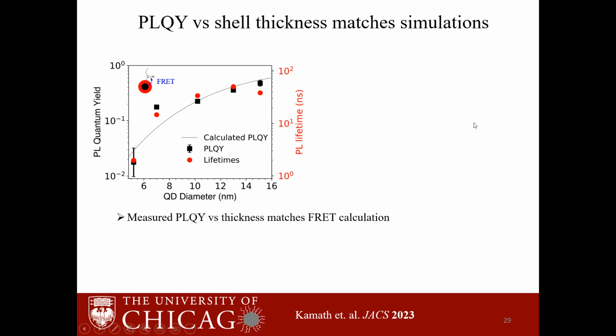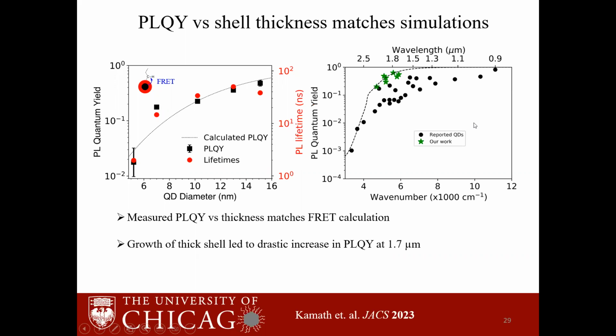And this is a further confirmation that the ligand FRET is not just dominant in the midwave, but also in the shortwave infrared. When we plot our quantum yields with the reported dots, we see that the quantum yields are much brighter than the previous materials. And while the previous brightest materials were emitting at a quantum yield of 20%, our quantum dots have a quantum yield of 60%.